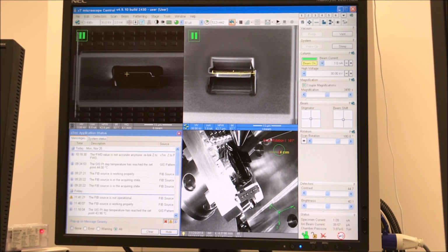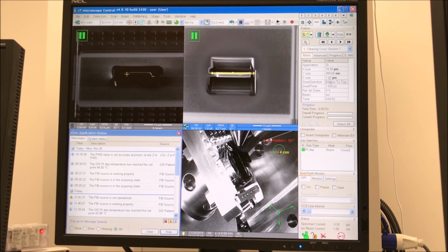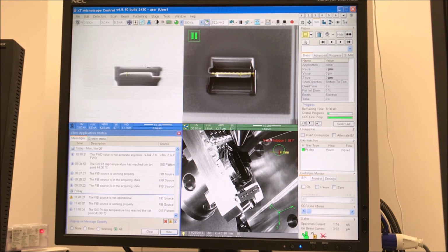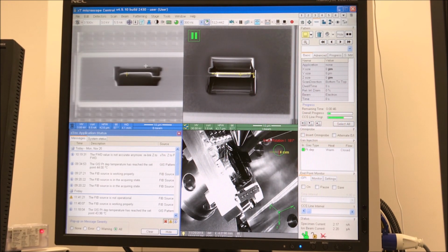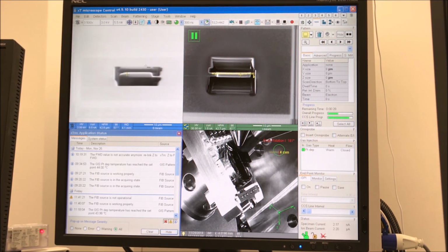And you can also see that the lamella is not quite perfectly level in the ion beam image. So I'm actually adjusting the scan rotation of the ion beam image very slightly away from 180 degrees just to kind of square it up. And then I can execute the pattern. And in the electron beam image, we can actually see the side of the lamella as the cleaning cut is being performed.